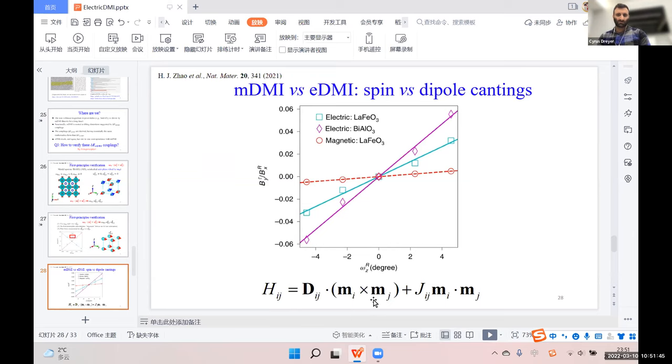So for the magnetic moment, it's bilinear. Well, in the electric DMI, this is a dipole, and this is UI and UJ. So you have trilinear coupling for the electric dipoles, hence the electric DMI and magnetic DMI. From the symmetry point of view, they are the same, but in reality, from the couplings, they are very different. So you will see typically, it seems that the electric DMI doesn't want to,